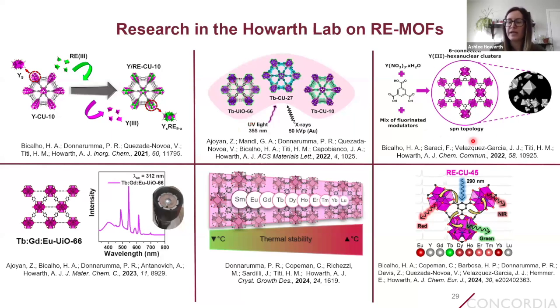We're also always looking to make new MOFs, and so this is the new MOF CU45, which is the first rare earth cluster-based MOF with open metal sites that's been reported in the literature. We've also shown that you can make mixed metal analogs of these rare earth cluster-based MOFs, specifically UiO-66, and by strategically tuning the composition of terbium, gadolinium, and europium in that cluster node, we can generate a MOF that has white light emission, which is of interest for solid-state lighting applications.